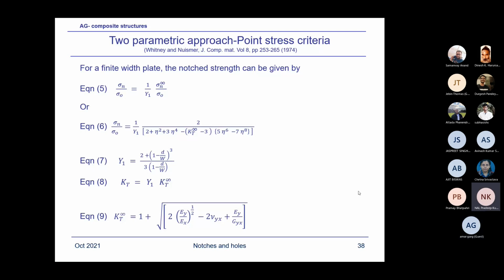Sir, normally we consider the critical strain energy release rate. Yes, so that is one. And again, you said limit load also. So should we consider both together? No. Look, when we say limit load, that is the capability of the structure to carry the limit load, a static load. Then for that limit load you calculate the strain energy release rate. That's a different thing. You apply that load in order to calculate the strain energy release rate, and when it becomes critical, then the fracture would occur. So that will be the residual strength prediction based on the critical strain energy release rate. Yes, both happen together, sir. It's a criteria at the same location. Essentially we are deriving the limit load out of the critical strain energy release rate.